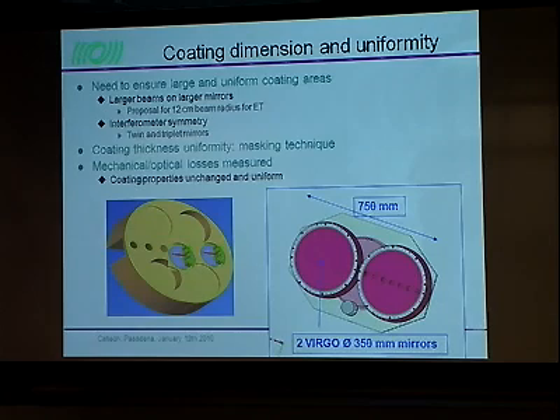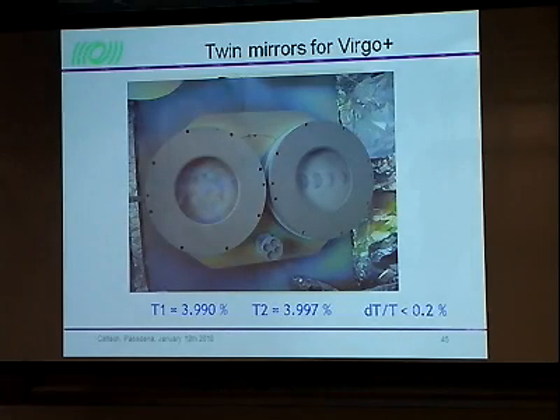So this work was done, the result was positive, and based on this study we were able to produce the first twin mirrors for Virgo Plus. So two large mirrors were coated at the same time, the two input mirrors of Virgo Plus, and the transmissions which were measured were very, very near one to the other. The difference in the transmission was less than a percent, which I think is the best result obtained with such large mirrors.